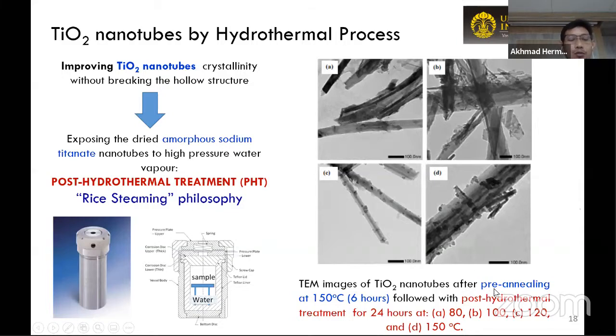Then we thought about how we can improve the nanotube's crystallinity while at the same time maintaining the hollow structure. If we do the calcination, the crystal size can grow significantly, but at the same time the nanotube will collapse. That's why we thought of one way to improve the crystallinity of the nanotube and maintain the hollow structure, by using post-hydrothermal treatment. Previously it was hydrothermal treatment, and this stage is called post-hydrothermal treatment.